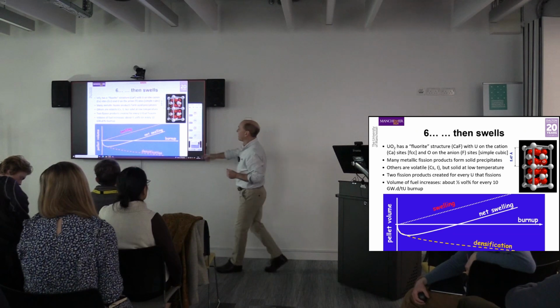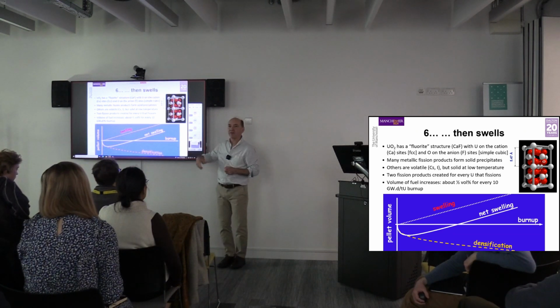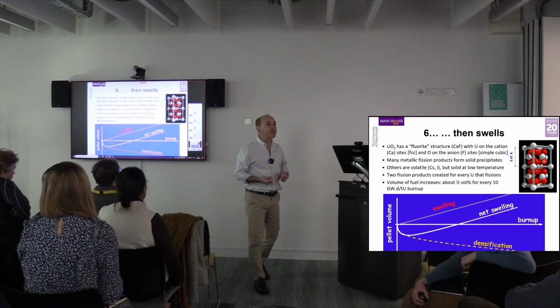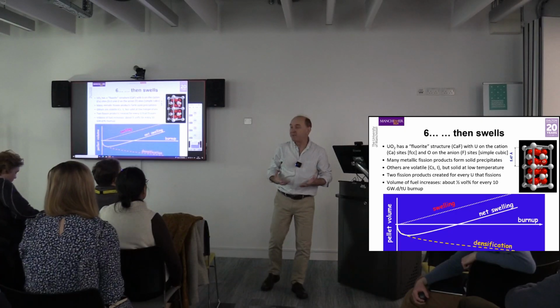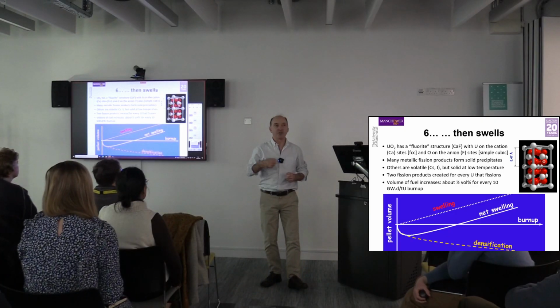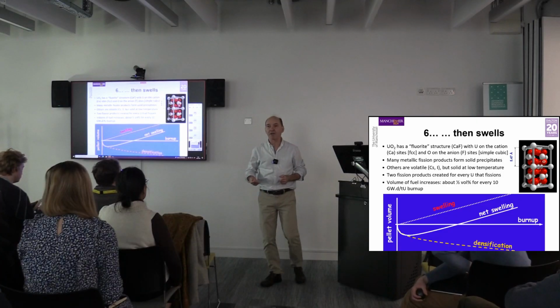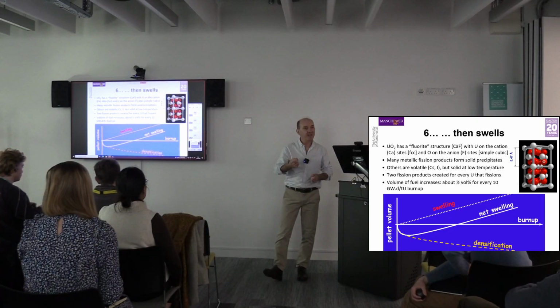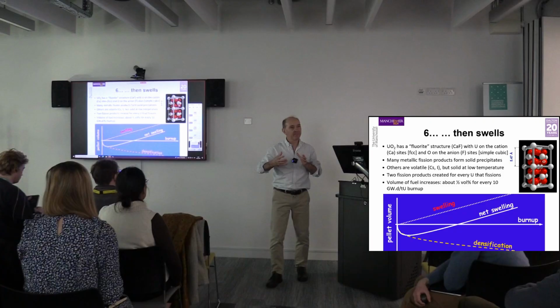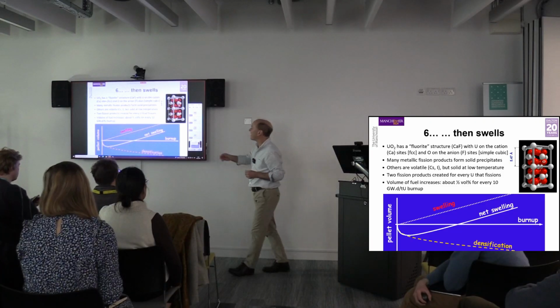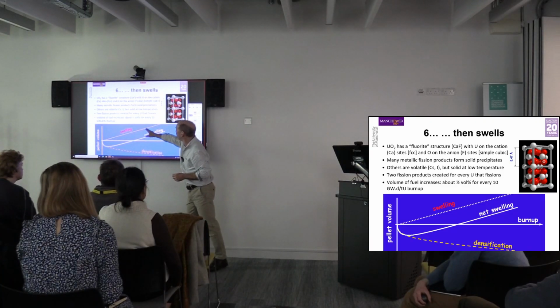And that swelling is just a linear function of burn-up. Burn-up, remember, is just the amount of energy that we get from the fuel. It depends on the number of fissions. You double the fissions, you double the burn-up. But every one of those fissions is causing swelling. So the more and more energy you get from the fuel, the more and more and more it swells.